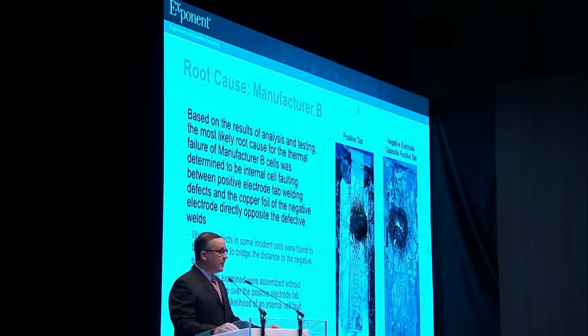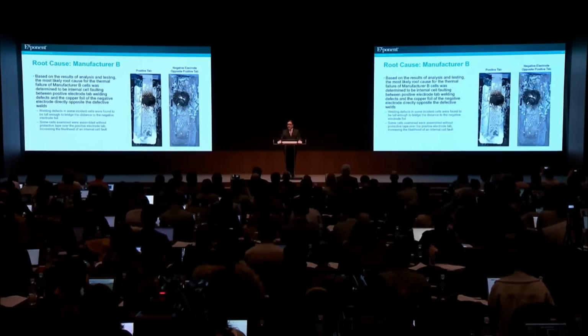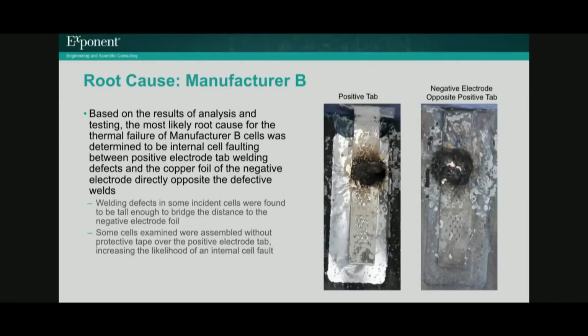Following the expanded recall on October 16th, Samsung asked Exponent to perform an analysis of the Note 7 devices containing cells from manufacturer B. As I mentioned previously, these new devices contain cells that were manufactured after our initial investigation of batteries A and B. Exponent's findings related to the thermal failures of cells from manufacturer B showed that manufacturing defects on the welds of the positive tab were able to bridge the space between the positive tab and the neighboring negative electrode, resulting in cell faulting and, in some instances, thermal runaway.